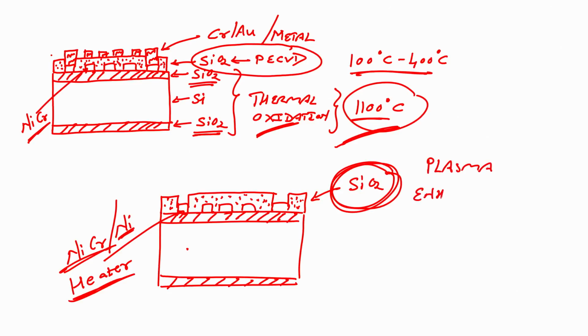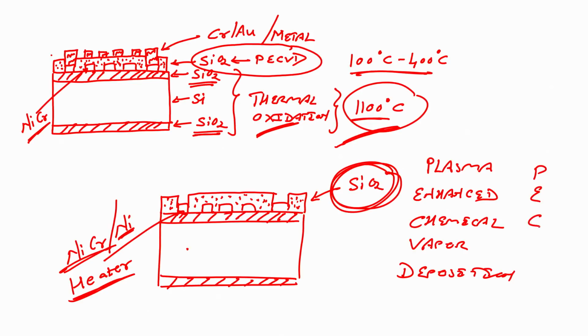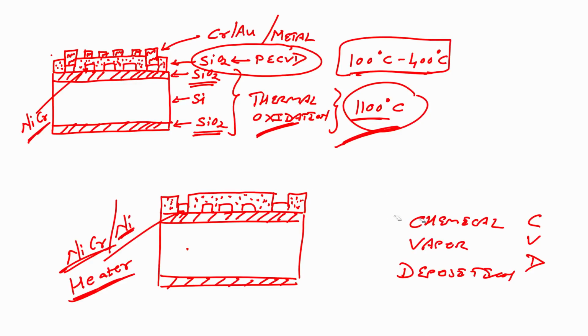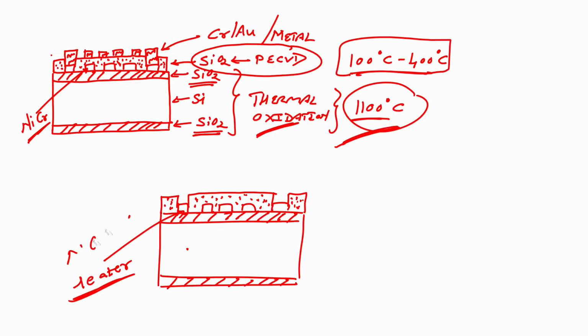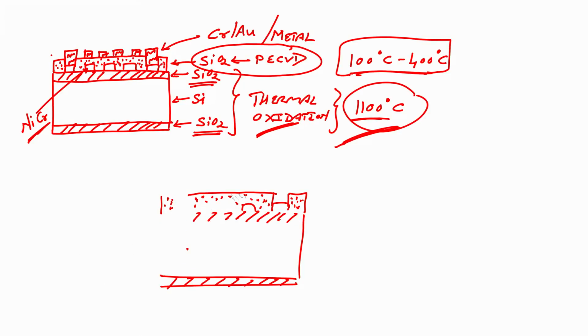So, to avoid that, I will deposit silicon dioxide using a technique called plasma enhanced chemical vapor deposition, right. It stands for PECVD, right, and the advantage is that we can deposit at a lower temperature. You got it? That is why I said that for insulating layer over heater we will go for PECVD, right. So, that is the reason of using PECVD instead of the thermal oxidation. Okay guys, easy, very easy, right.